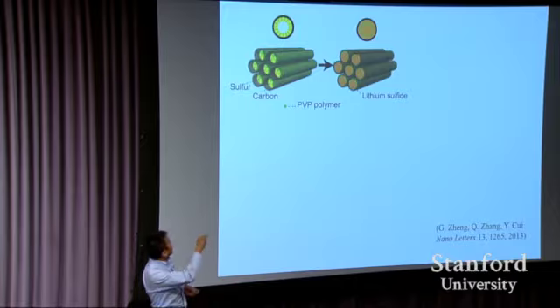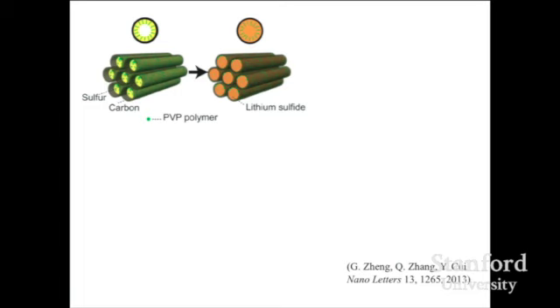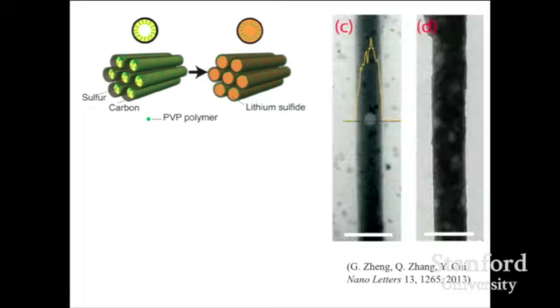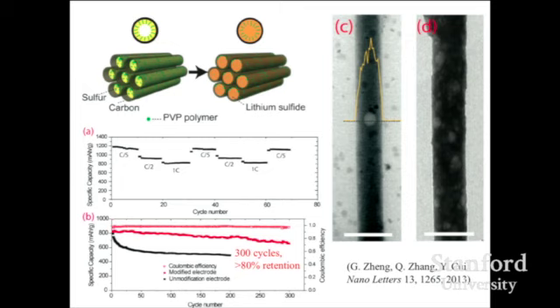Now we put PVP polymer inside and then coated sulfur inside. And after you cycle this, before and after, you don't see those bead-up phenomena anymore. The battery cycles right here, 300 cycles, quite stable. So we finally think we got it using this understanding. And more cool ideas come in.